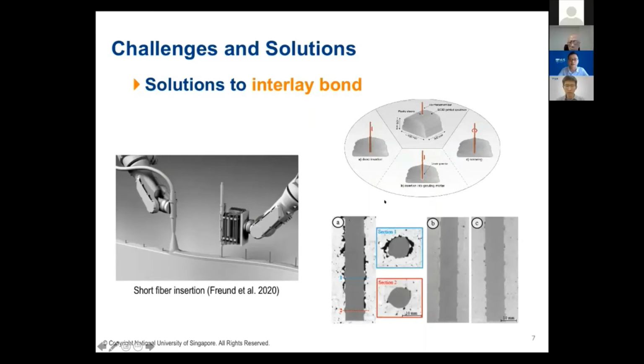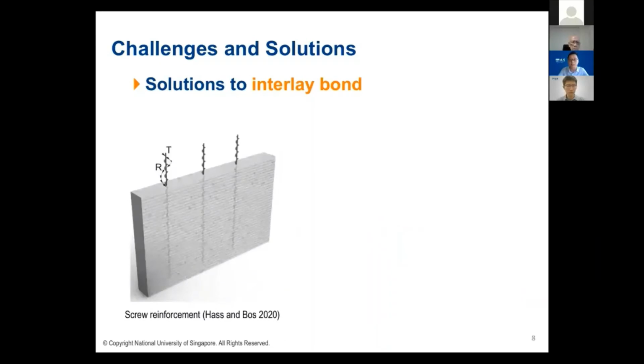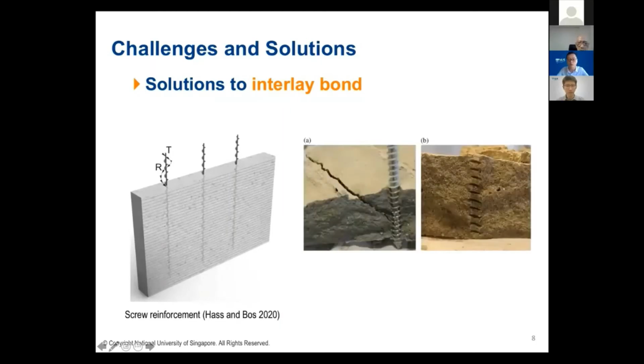So they gave a very good result, showing the interfacial performance has been greatly improved. And similarly, some researchers in the Netherlands use this screw reinforcement. So basically, they are using the same idea, mechanically increasing the interfacial performance. And this photo shows the pull-out test. They pull the screw reinforcement out from the concrete. There are some cracks after pull-out. The results are also very encouraging.